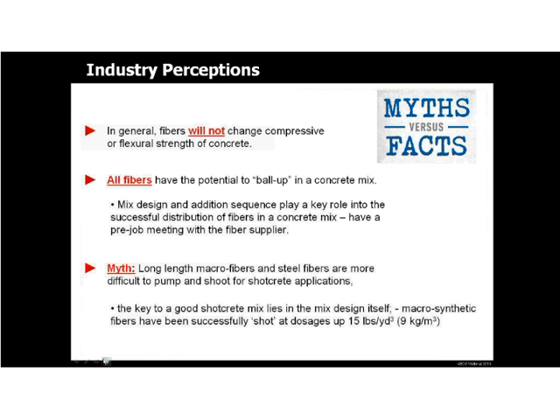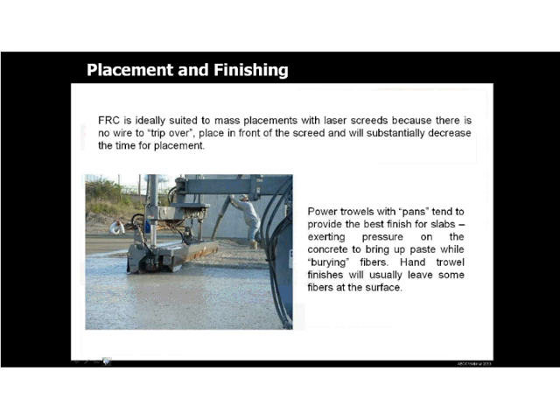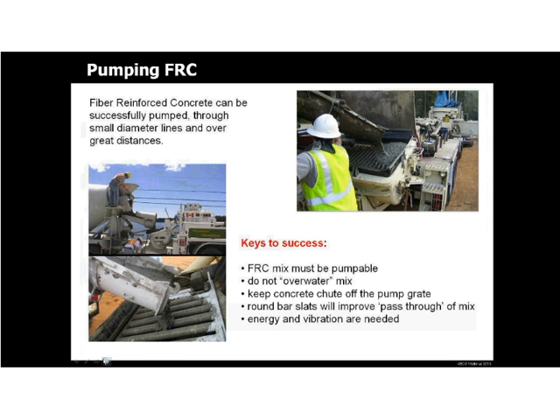Some of the other items, too, that occur with regards to myths include the use of trying to pump fiber-reinforced concrete. And it really is a myth with regards to the fact that long-length fibers cannot be pumped. Many successful applications have pumped steel fibers and macrosynthetic fibers over significant distances. There are, again, some tips and tricks to the successful use of fiber-reinforced concrete in pump applications. The first item being, of course, the mix design needs to be pumpable on its own. We do not want to see mixtures overwatered for the slump loss. Essentially what that's going to do is potentially segregate your mix through the line, squeezing the juice out of the concrete and basically leaving a fiber clog or a ball.